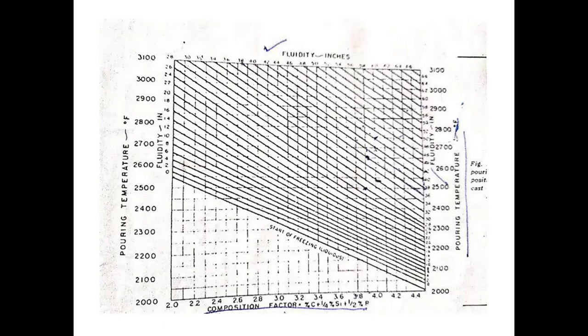At that time, basically fluidity is very important, because the coldest metal is going to come on the top of the box. If the wall is 6 mm or 7 mm, the surface area will be flat. At that time, the pouring head works. If the pouring head is not there, then naturally in the cope box the blowholes will be there. So at that time, the coldest metal comes at the top side, basically. In that case, this fluidity factor is important.